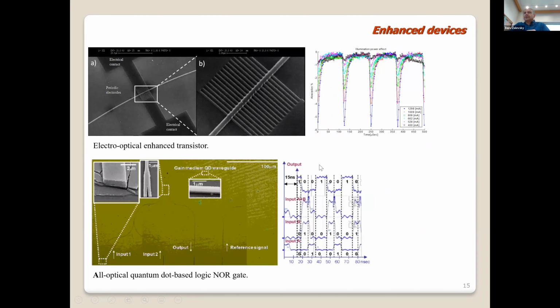We also try to enhance the nonlinear effect that you inherently have in silicon. The inherent effect is the plasma dispersion effect. To enhance the effect, to allow smaller modulation voltages that will still allow a strong modulation of the photonic information guided through the photonic waveguide, we fabricate, for instance, electrodes which are not conventional electrodes, but have a Bragg structure. And by that, when we apply voltage on those electrodes, due to the plasma dispersion effect in silicon, we generate a periodic change in refraction index, which affects the information photons more strongly.